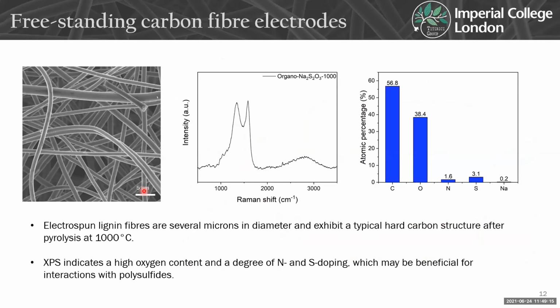So this is what the fibers look like. They're several microns in diameter. And from the Raman spectrum, you can see that they've got typical hard carbon structure after pyrolysis at 1000 degrees. But if you increase the carbonization temperature, you can increase the graphitization, but then the mat becomes more brittle and quite difficult to handle. And then we can see here from the XPS that we have quite a high oxygen content in these fibers and some degree of nitrogen and sulfur doping.